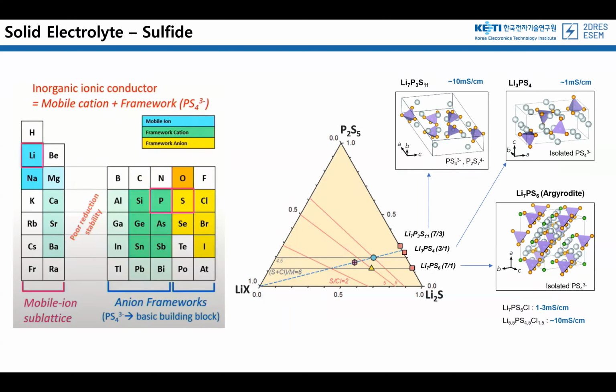Sulfide-based solid-state electrolytes are made of anion frameworks and lithium cations. They typically use a combination of phosphorus and sulfur, such as lithium thiophosphate, to create the solid electrolyte. Li3PS4 is the most stable combination that has been isolated with lithium ion. However, when it is highly crystallized, the ionic conductivity is low. By adjusting it to a glass type, it can reach 1 millisiemens per centimeter.